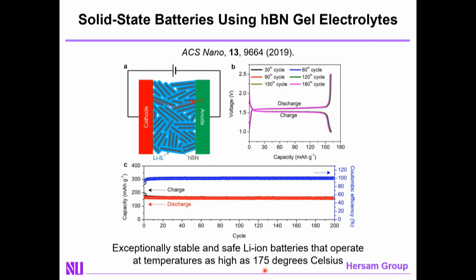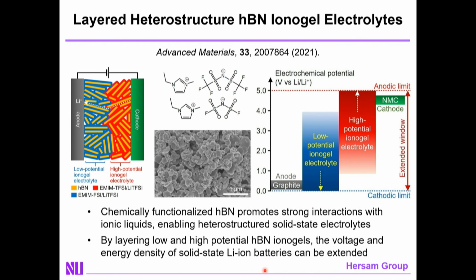So that all looks good, but there's a catch. And the catch is that if you look at the full electrochemical stability window of the ionic liquids that we're using, you see that it goes down to only 1 volt. You can go up to 5, as I showed you before, but only down to 1 volt. So the delta V is only 4 volts. That does not allow you to use conventional anode like graphite on the anode side of the battery.